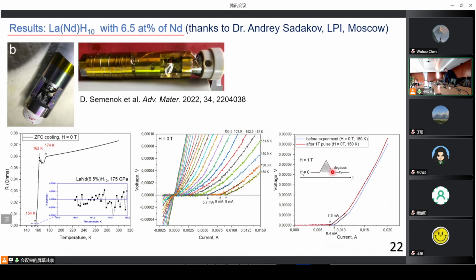Okay, in the first experiment we just made the same pulse as was done in Minkov's work. We just switched on the field and switched off the field. And after that, after degaussing of the magnet to remove the residual magnetic field, we measured again this critical current and found that there is a hysteresis loop. And the critical current is now much smaller.